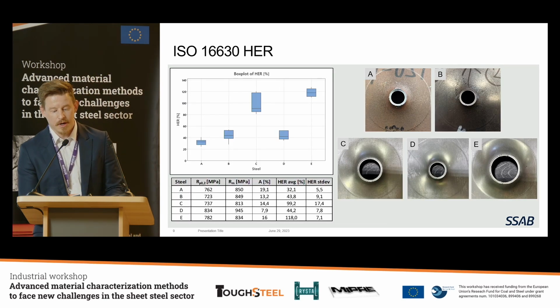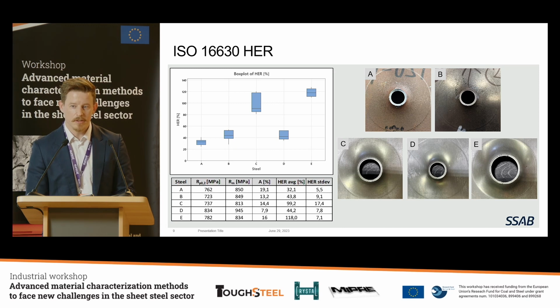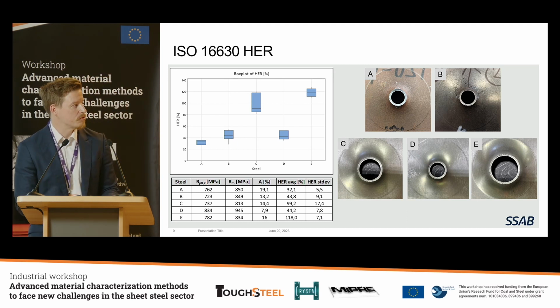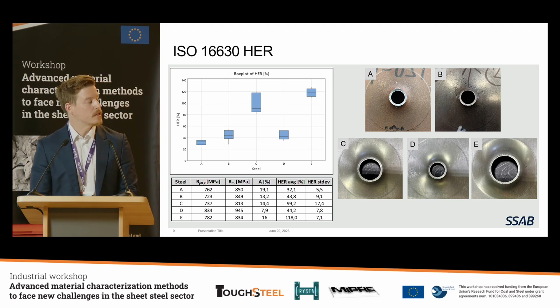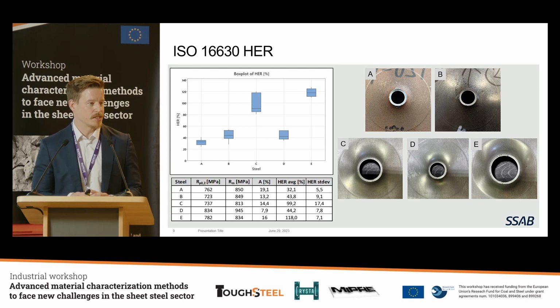Then starting the results from hole expansion, and actually you can see that we have 2 different levels of results. 3 of the materials are on a, let's say, normal level of these hot-rolled steel grades above 700 megapascal yield. They are normally around 40% of hole expansion results. But 2 of the steels are showing really high levels of hole expansion ratios, over 100%. And actually this is creating now interesting variation of these materials, even though the normal mechanical properties are looking almost the same.